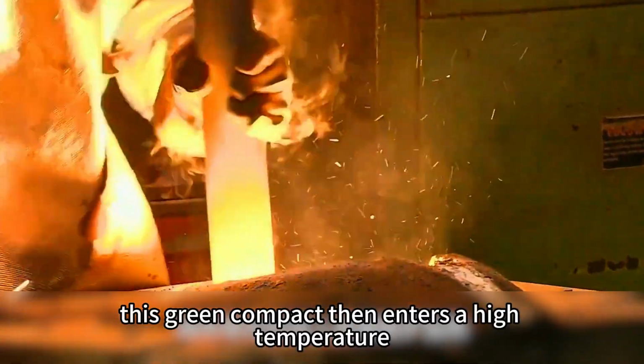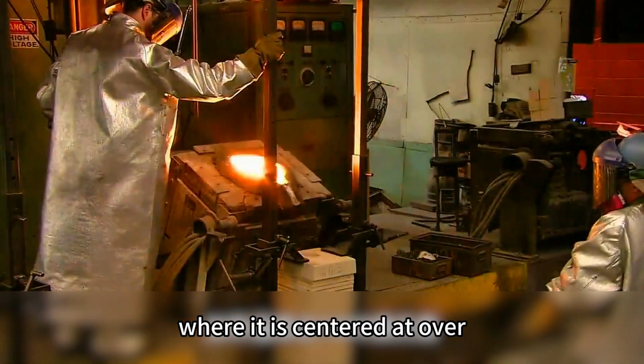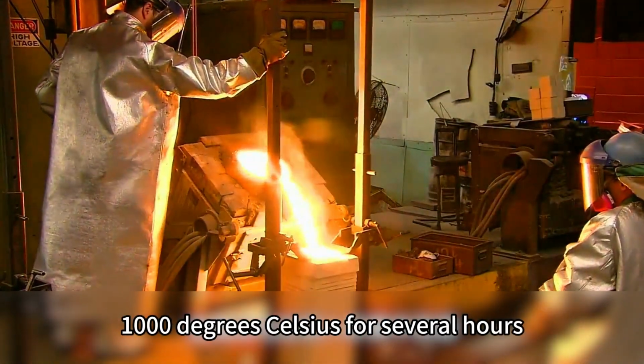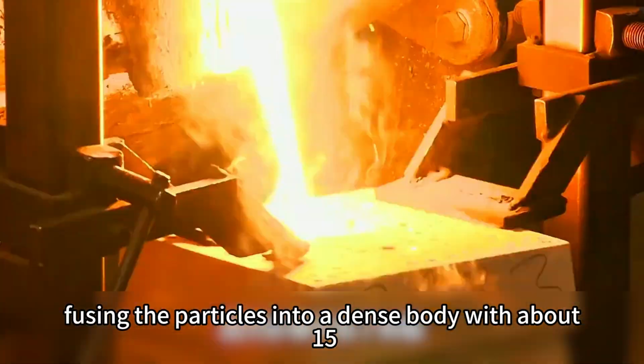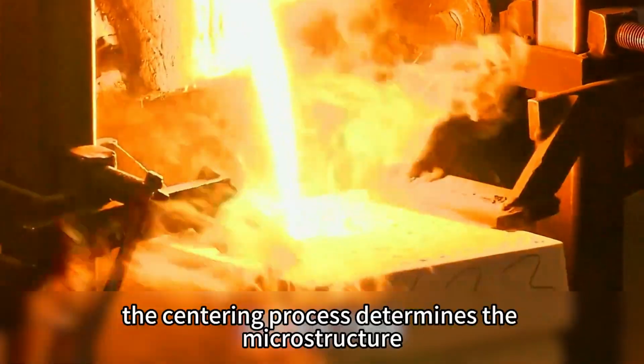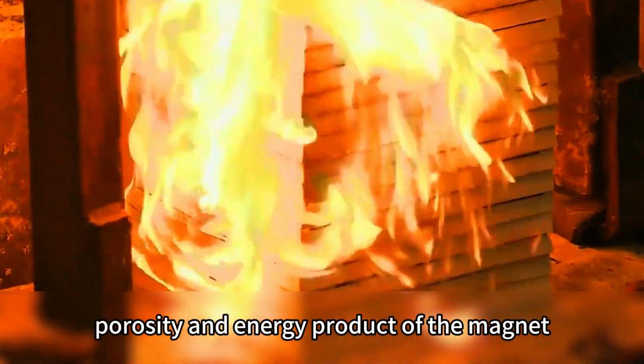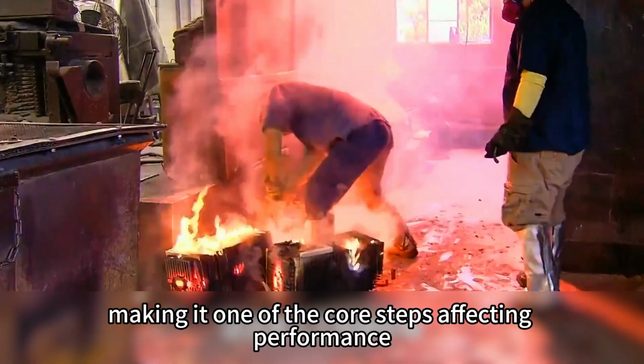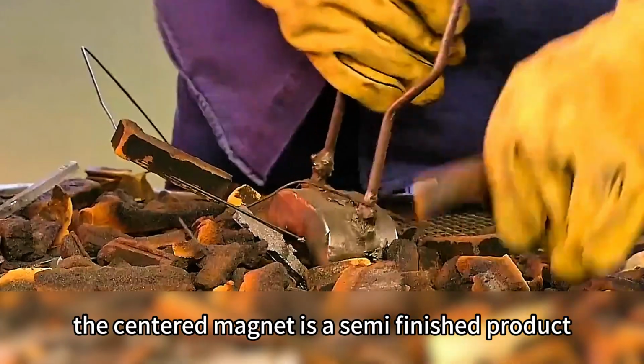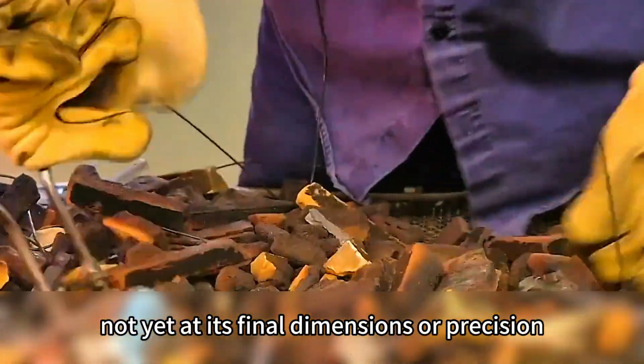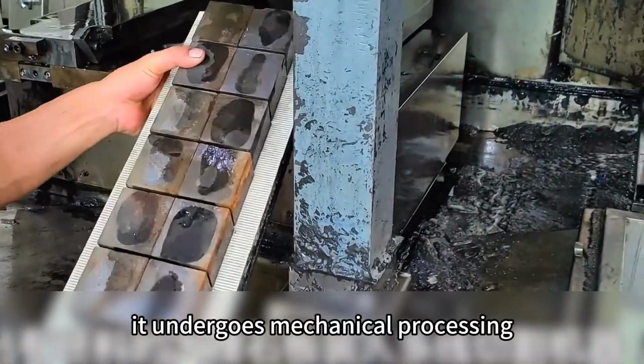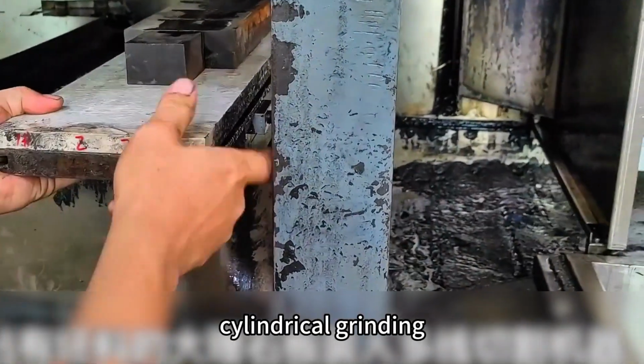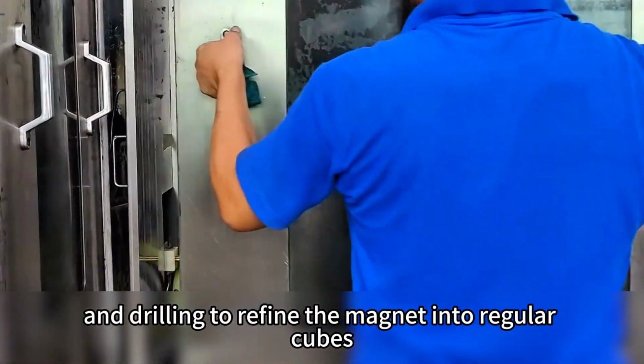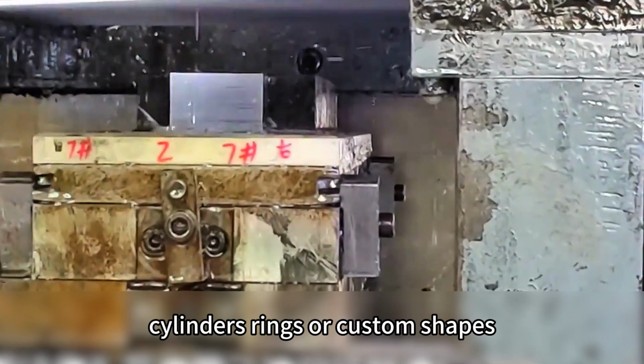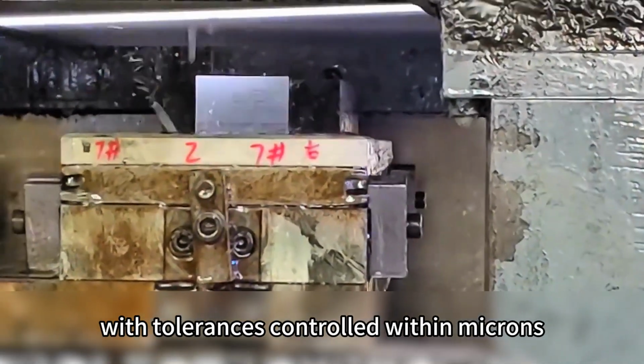This green compact then enters a high-temperature sintering furnace, where it is sintered at over 1000 degrees Celsius for several hours, fusing the particles into a dense body with about 15% volume shrinkage. The sintering process determines the microstructure, porosity, and energy product of the magnet, making it one of the core steps affecting performance. The sintered magnet is a semi-finished product, not yet at its final dimensions or precision. It undergoes mechanical processing, including wire cutting, cylindrical grinding, surface grinding, and drilling, to refine the magnet into regular cubes, cylinders, rings, or custom shapes, with tolerances controlled within microns.